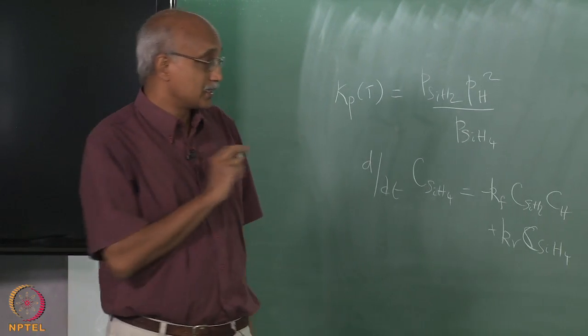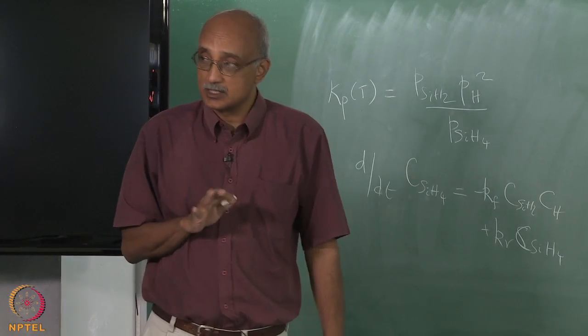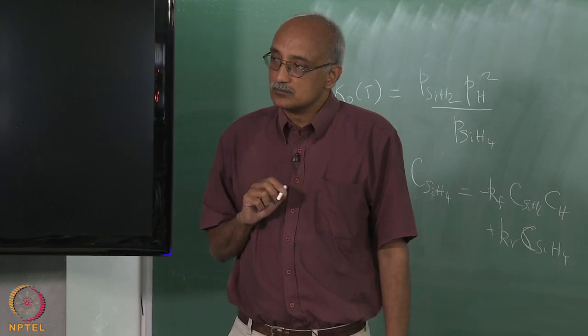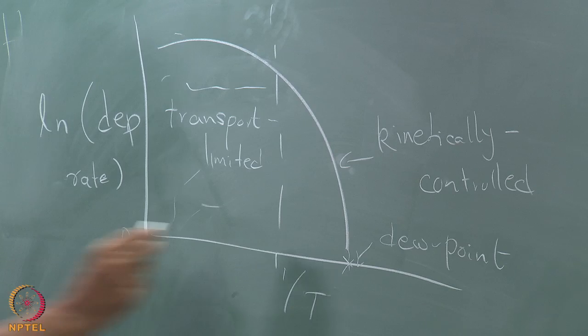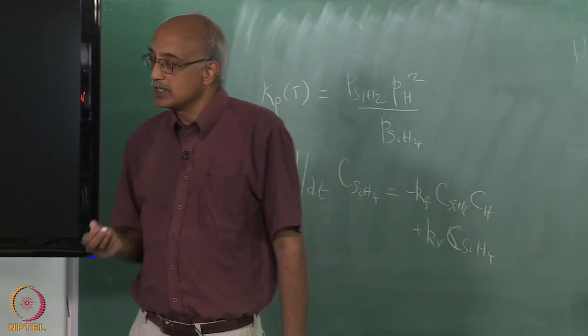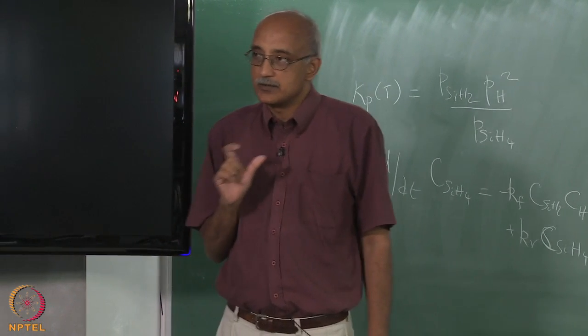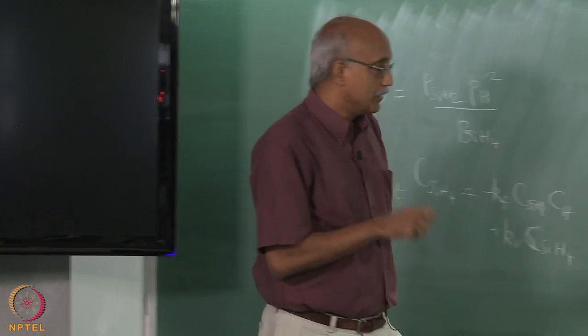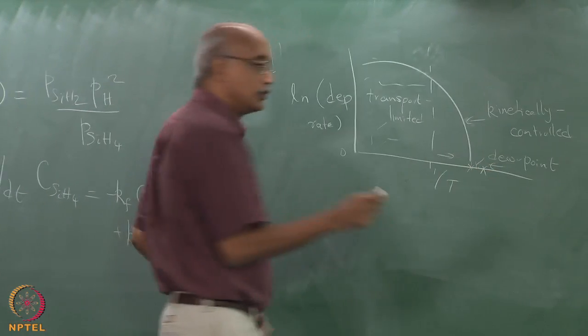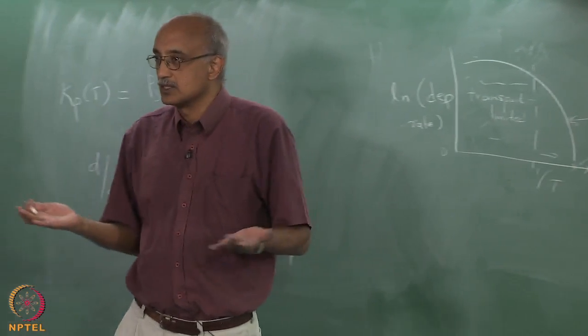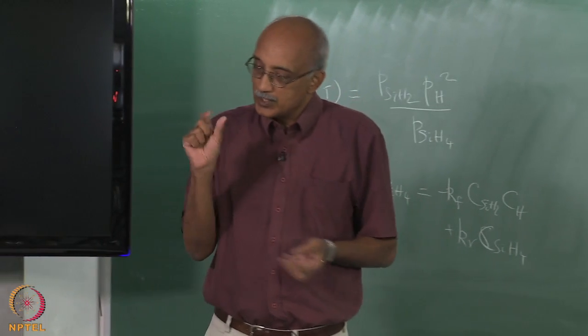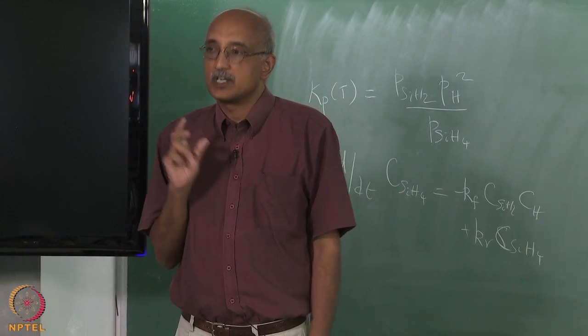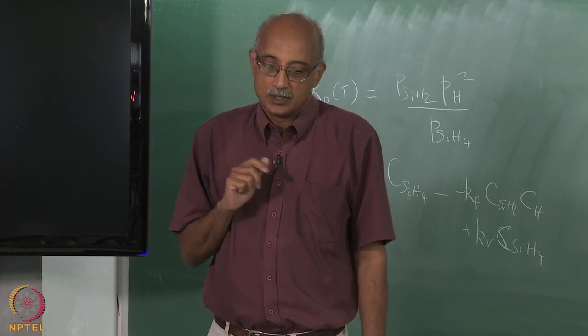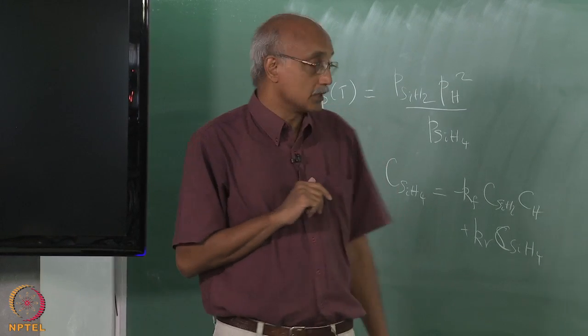But one thing that is unique about dew points in CVD systems is that they are not unique. In other words, depending on whether you approach the dew point in this direction or in this direction, the dew point may be different. So, we will talk about that again in more detail, because that is a very, very crucial thing to understand in CVD reactors. And in fact, the behavior of the film between the two dew points, it is like a hysteresis effect, very simply. But when the temperature is between these two dew points, the film has some very, very interesting characteristics that can be exploited for certain applications.